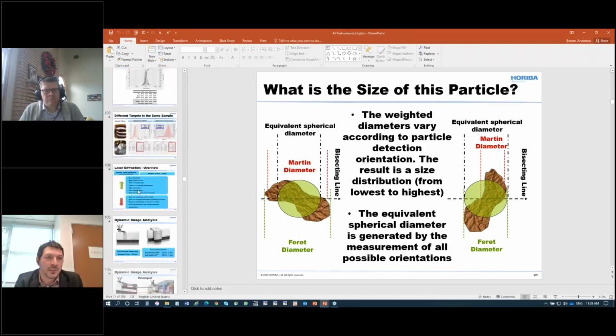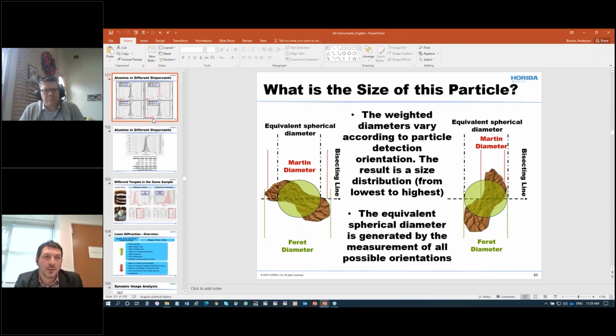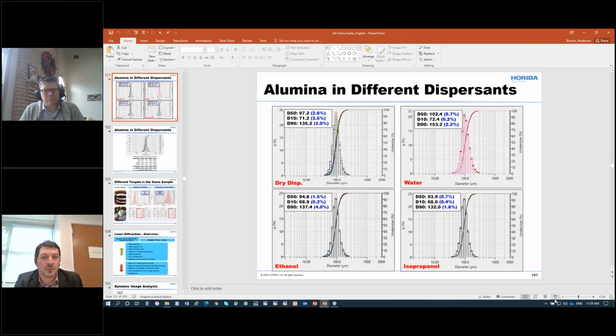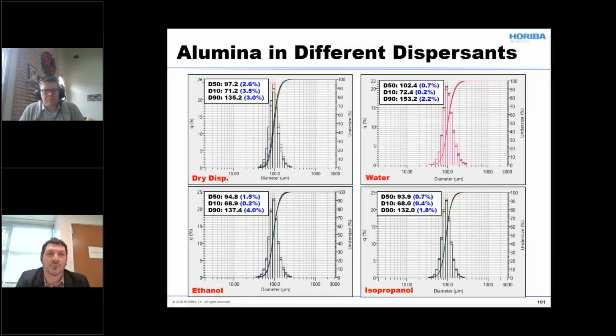You have the results in different mediums. As long as you have a good dispersion, you have very repeatable data. So here I have alumina, which is a very easy material to disperse. And you see here I have the dry dispersion, dispersing in water, and in ethanol and IPA. Here are triplicate results, actually 9 runs for every sample in every dispersion medium, including the dry.